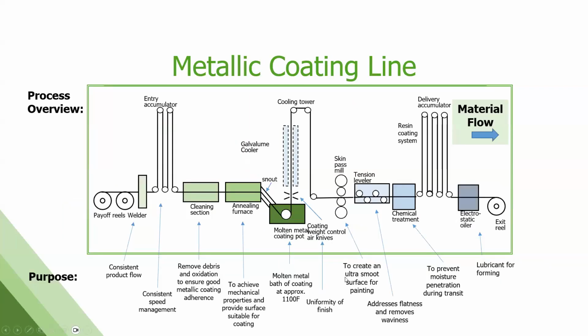This is a very generic schematic of one of these metallic coating lines. They are very, very large, often 7, 8, 9 stories tall. They are very long. They hold anywhere from 2,500 to 5,000 linear feet of steel from end to end. They run at 150 up to 600 feet per minute, depending on your line and how old it is and how it's configured. So very, very fast, very efficient. There's more going on here than just applying this metallic coating though. We're also determining the grade of steel and what its mechanical properties, structural properties are going to be.